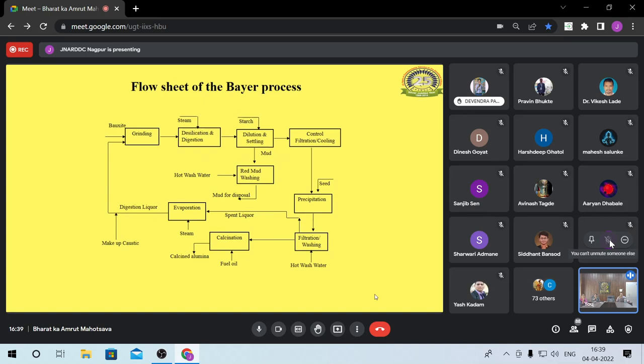Whenever we add any seed, it provides nuclei for the precipitation to occur. The time required for precipitation in a continuous operation is around 50 to 55 hours, so it takes a lot of time for the precipitation to take place. After the precipitation is over, the precipitated slurry is filtered, washed, and the washed hydrate is then sent for calcination, where it is heated to around 1100 degrees, and the spent liquor goes for evaporation for concentrating it further.